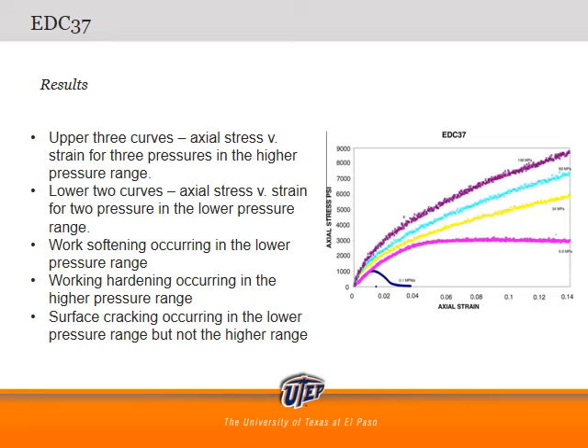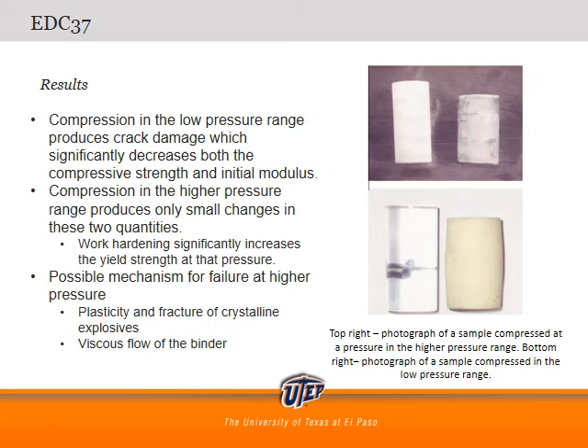As you can see, there is a peak in the axial stress in the lower 2 curves indicating work softening occurring. However, in the upper 3 curves, work hardening occurs, allowing them to withstand higher stress. It is also observed that surface cracking occurs in the lower pressure range but not in the higher pressure range. Compression in the low pressure ranges produces crack damage, which significantly decreases both the compressive strength and initial modulus of the material, allowing for work softening to occur.